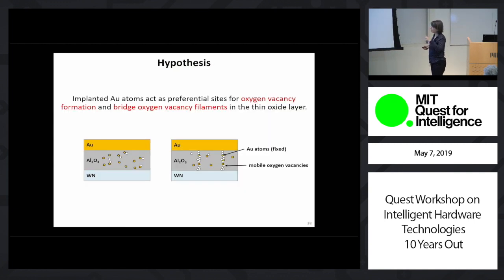So our hypothesis after having seen this procedure and the result was that with FIB milling, most likely we are implanting gold, and I will show other metals, into the alumina. And Zhengji has run ion implantation and sputtering calculations, simulations that show that you can have a significant amount of gold implantation into the alumina under his FIB milling conditions. And these implanted metals, in this case gold to start with, serve as dopants, and that can alter the ease of reduction, ease of oxygen vacancy formation within the alumina layer. And if so, then percolation of these easy to reduce zones could form a conducting path because of gold atoms inducing oxygen vacancies more easily when subject to large electric fields.